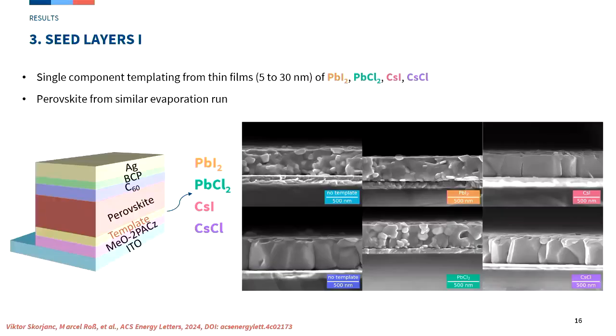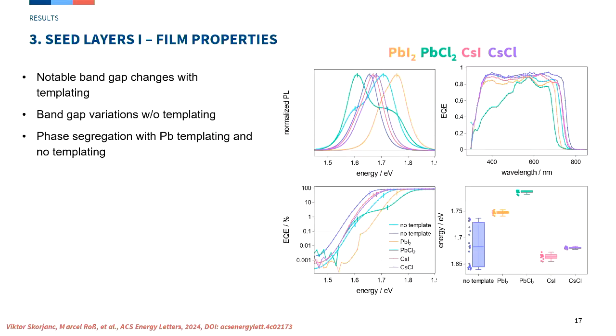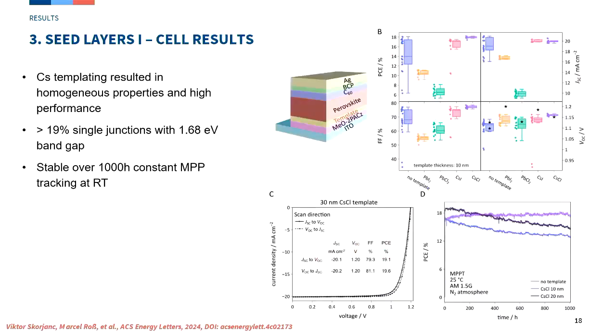Then you get films that are very nice again, with a much smaller spread, as you can see here in the optical properties, the band gap of those films. You see there's a spread, which is what you don't want to have. If you do form the right seed, then you get the perfect band gap for a tandem solar cell, 1.68, and the spread is much lower. Also in the quantum efficiency you see that band gap change, with no sub-band gap absorption or halide segregation, which for some cases you do see as a double emission peak. That's what you don't want to have. If you use the correct seed layer, this is going to be right.